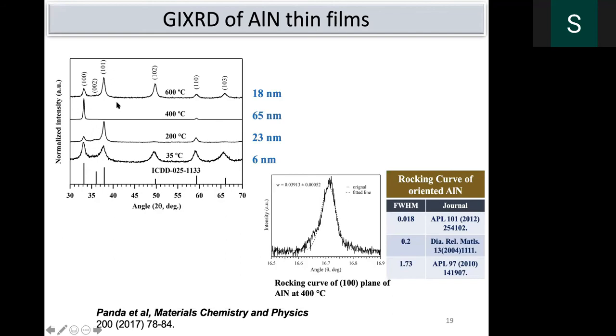When you take this particular 400 degree centigrade grown film and study it by rocking curve, what you are doing is fixing the detector at around 33 degrees and just tilting the sample so that you get a profile. The width of this rocking curve tells about the single crystal size. If the peak is one sharp line, that means it's a very large crystal. But if the width is increasing, that means they are polycrystalline. From that we normally calculate, using the Scherrer formula, the size of the grains. Crystallite size we always calculate.